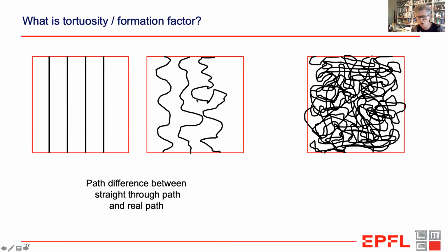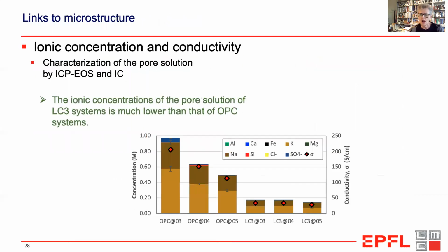So it's really important to understand that these measurements of tortuosity go far beyond what we can imagine from simple geometry. Really, these measurements are hiding something else we don't yet well understand. We saw also in these systems that we get quite big changes in the alkalinity, which also seem to show some relationship to the conductivity. But again, this is explaining perhaps half the variation.